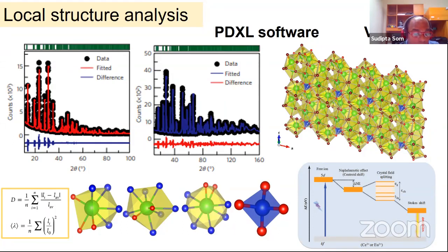Then we can evaluate the bond length distortion index and elongation factors from the refinement data as per the formula given here. If the elongation factor is obtained near the ideal value for a perfect octahedron, it can indicate high symmetry. And if the bond length distortion index is large, then the 5d orbitals of the activator result in large splitting, which may cause a broadening in the emission. So a promising symmetric environment may lead to a highly efficient and stable phosphor. By this structural analysis, we can optimize any phosphor material with a highly rigid structure.